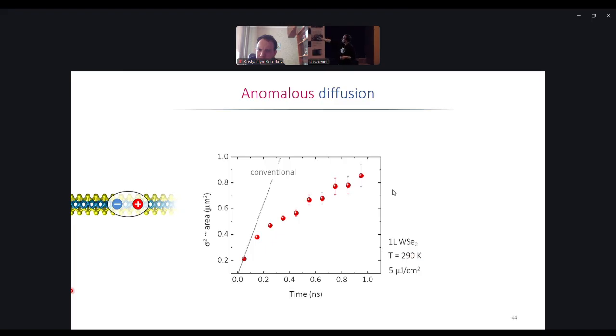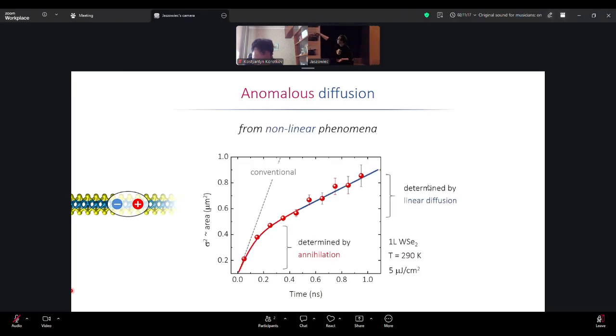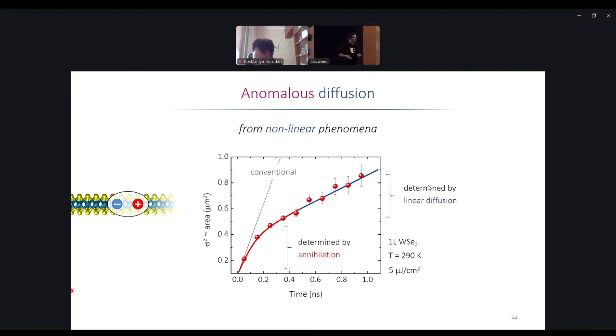Now, a measurement that shows this phenomenon will then show that the area does not expand linearly, because in the beginning, it's dominated by annihilation, and then towards the end by linear diffusion. Okay.